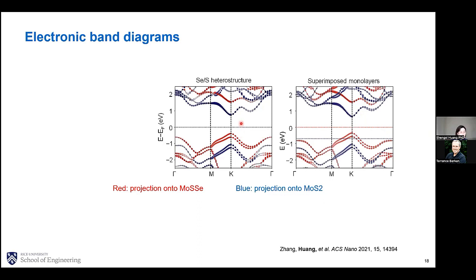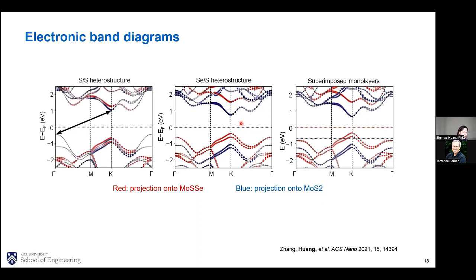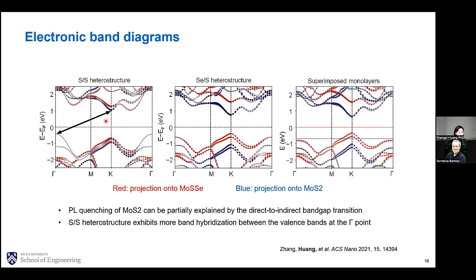But now if we look at the SS interface, things become dramatically different. You can see for the SS interface, the band diagrams actually change from a direct band gap to an indirect band gap, as you can see over here. So this indicates a stronger interlayer coupling strength between the two layers for the SS heterostructure. All right, so these results match very well with our experimental observations.